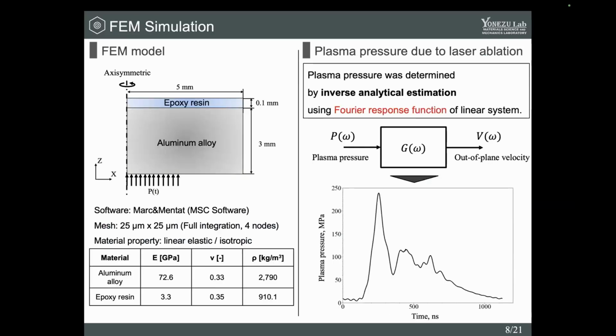In order to evaluate bonding strength quantitatively, we conducted FEM simulation. This is a detail of the FEM model. On the bottom surface of this model, plasma pressure of laser ablation was applied. This pressure history was estimated by inverse analysis using a Fourier response function.